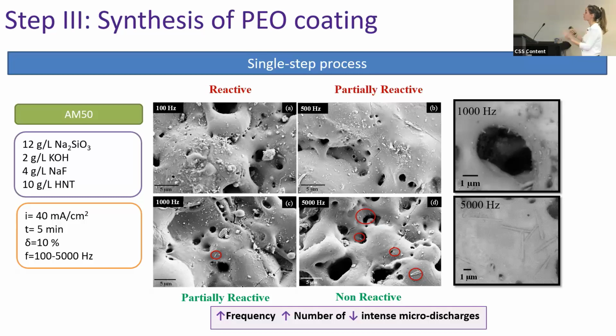So when we increase the frequency, we reduce the pulse times, and it results in a higher population density of microdischarges of less intensity compared to the microdischarges that we observed at low frequency, where there is a lower amount of microdischarges, but these are more intense. So can we say that these results are successful? Well, we learned that it is indeed possible to optimize the electrical conditions to achieve the non-reactive incorporation. But the total amount of incorporated nanotubes was so low that I don't think they can have a significant influence on the overall corrosion resistance.